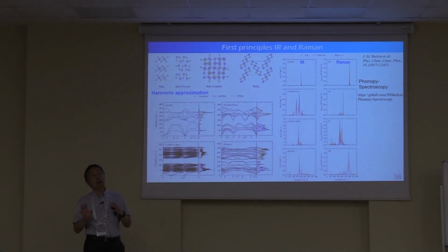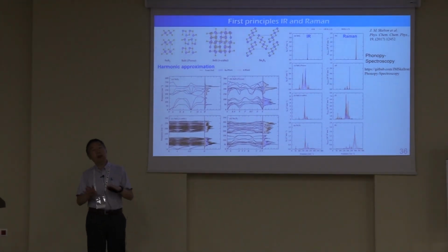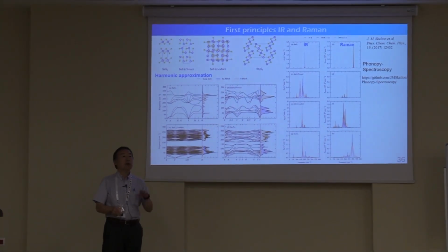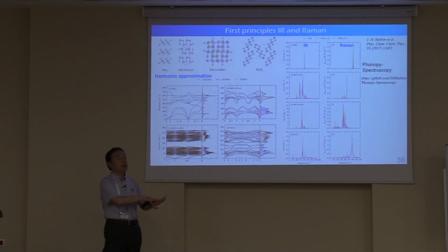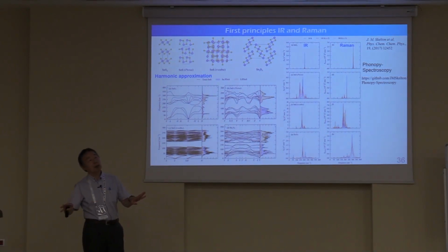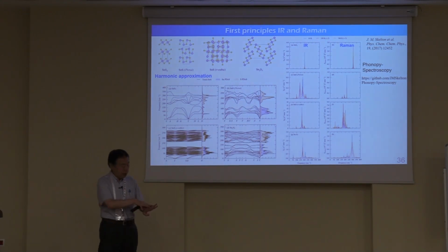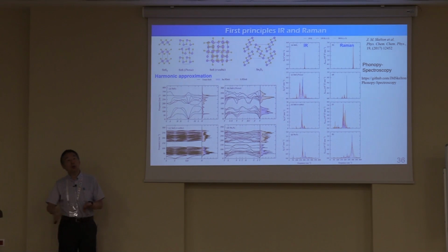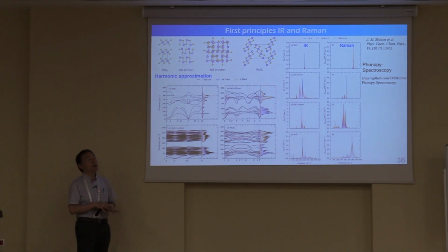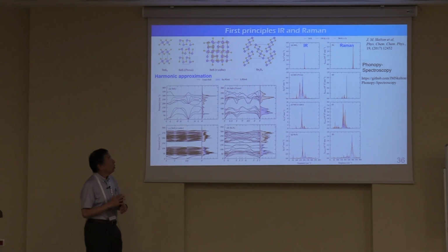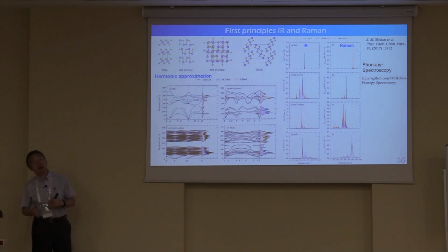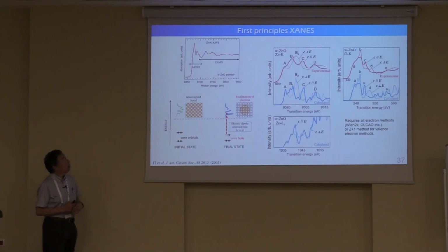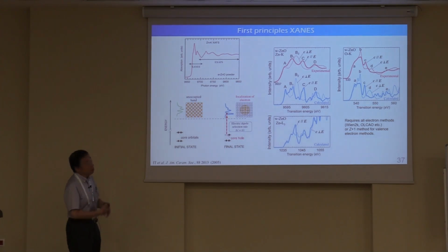Typically IR and Raman are characterized by the fingerprinting technique. If you have some reference material and reference spectra, and the material you synthesize fits this fingerprint, it is that material. In that way, infrared and Raman have been used. But now we can obtain a fingerprint by theoretical calculation. So you do not need a reference material prior to your experiment. This is useful. This is also true for X-ray absorption fine structure.